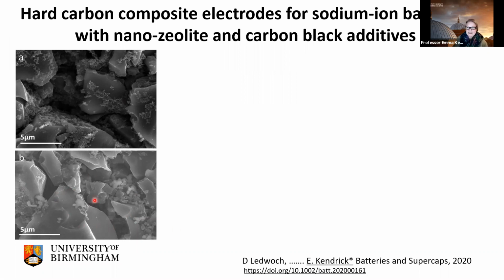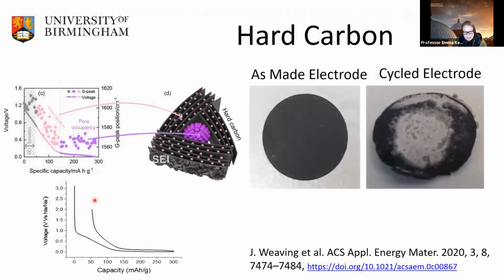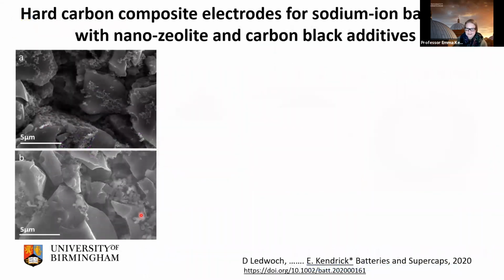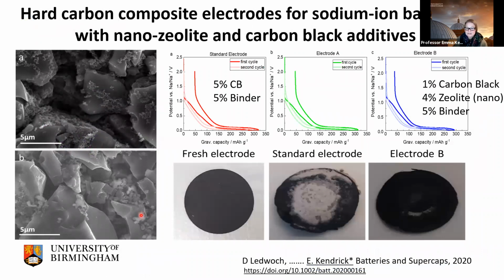And this is mainly because if you go back up to this graph here, this flat plateau has very, very slow diffusion properties as we're creating these little nanoclusters of sodium. So we thought we'd try and help it somehow by improving the electrode properties. And to our great surprise, it actually worked.